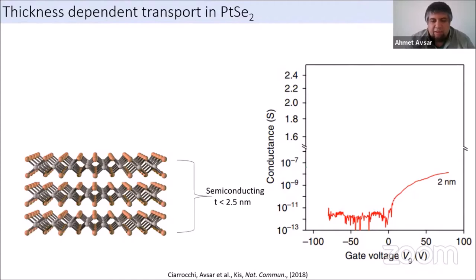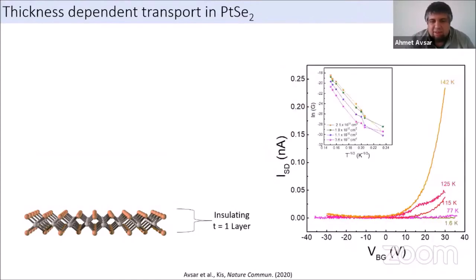Getting a monolayer of this material was extremely challenging, and we could only get it last year. What we could see is that the monolayer is fully insulating. It's a very insulating material; even applying a high bias, we don't see a good conductance. Based on the analysis, it has two-dimensional variable range hopping type transport from low temperature to room temperature at any carrier concentration that we had. So it's an interesting material. It shows metallic, semiconducting, or insulating properties depending on the number of layers you have.